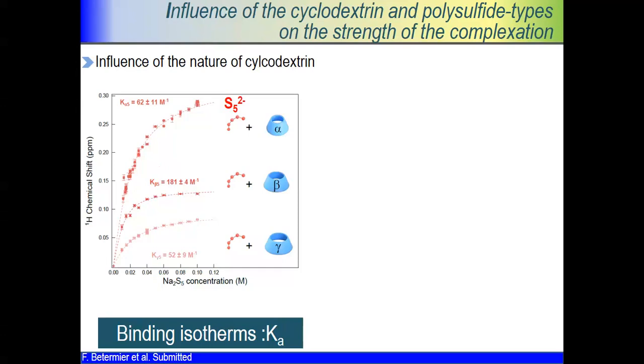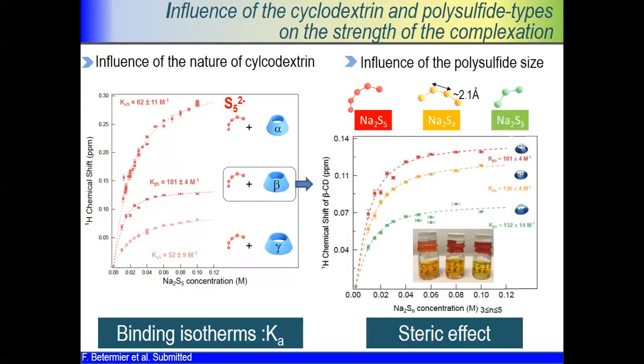So having this, we now use this beta cyclodextrin, and we try to see if we have a different type of selectivity between the different polysulfides. And this is more or less a curve that I represent here, and you can see that you indeed have an influence. Of course, the S5 is the most sensitive, while the S4 and the S3 minus have less activity with respect to cyclodextrin. So this is more or less a steric effect.